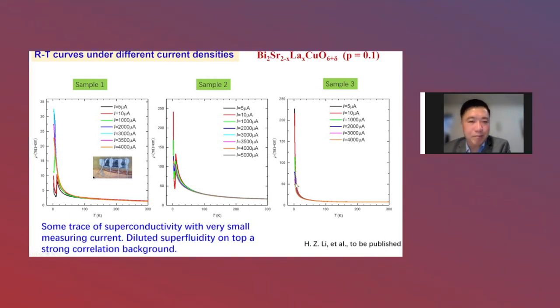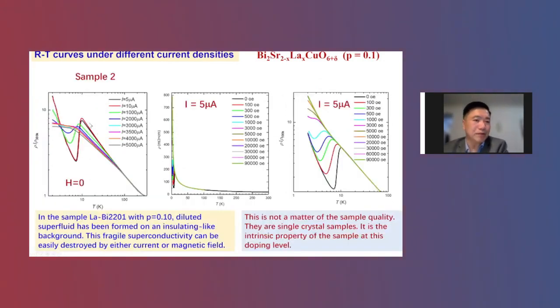If we take sample 2 and blow up the transition part with different currents, you can see that even for this sample, with a very small current, we see the superconducting transition. Okay, and this transition seems to be suppressed by the current and also by magnetic field. You can see that with a small current, you can see the superconducting transition. However, when you apply a field, then the transition gradually smooths out. So even for this so-called sample on the boundary, supposed to be a non-superconducting sample, when the measuring current is small, you see a superconducting transition.